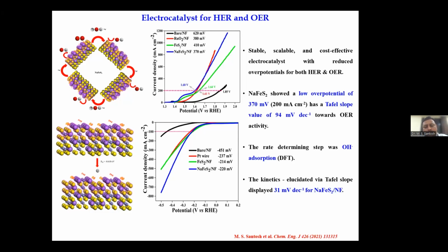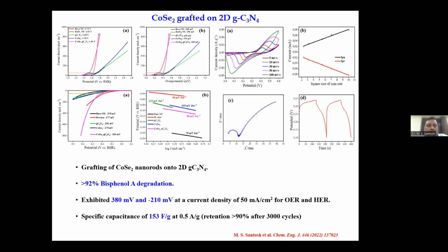And while elucidating the kinetics, it is quite evident that the Tafel slopes clearly display 31 millivolt per decade for the electrocatalyst developed. And this is a clear indication that the material behaves very positively for both hydrogen and oxygen evolution reactions. On the other hand, we also tried to come up with another material, which is cobalt selenide in combination with graphitic carbon nitride.